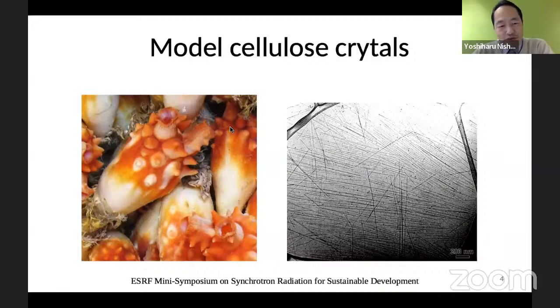So what we do is isolate it from a special organism. On the left-hand side, this is a tunicate, which is a sea animal that, when adult, sticks on a rock and doesn't move. It produces a cellulosic tunic, which is very highly crystalline and has the same crystal structure as wood cellulose. When you hydrolyze and disperse it, we get these very tiny rod-like crystals. Here the scale bar is one micron, and the single crystals are about 10 to 20 nanometers wide.